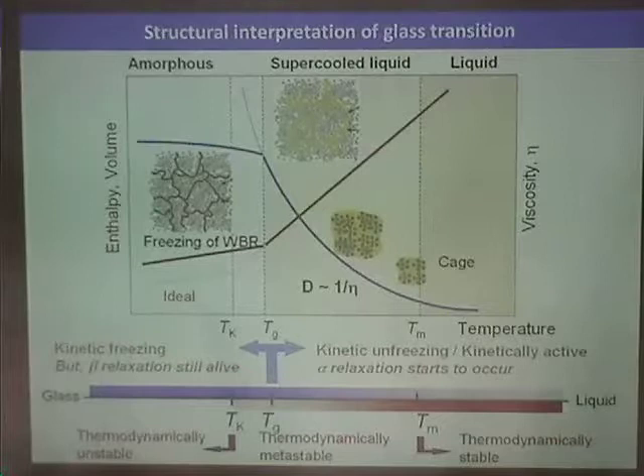No. But experimentally, if you look at window glass in church cathedrals that are 1,000 years old, they sag, they creep. It's not infinite. No, solids don't have infinite viscosity, just very large. Yeah, it just becomes large, but it's not infinite. You can just hang a weight on this and see what happens. At room temperature, over 10 years, 20 years, 30 years, it'll still creep. If it was infinite, then it would never change shape ever. But it'll age during the creep, presumably.